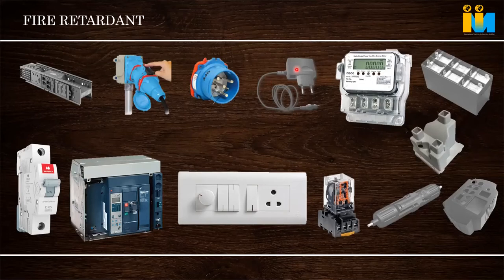These products call for a ball indentation test at 125 degrees. So ABS cannot withstand 125 degree ball indentation. Only polycarbonate can withstand it. That's why for this type of products polycarbonate is used, more than for the electrical property also. And when we come to other things, metering solutions like electrical meters are very important. Fire retardant transparent materials are used. It is a little bit costly, because whenever we add fire retardant to any raw material like PC, it loses its